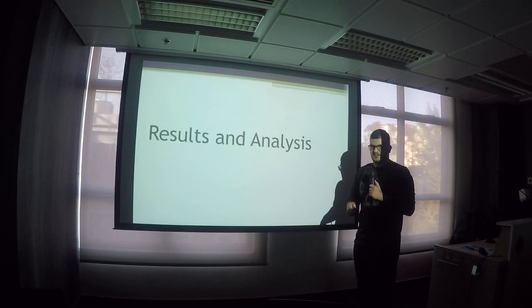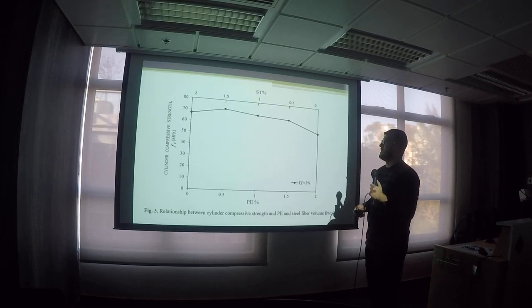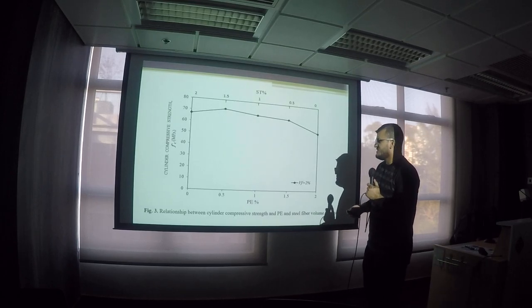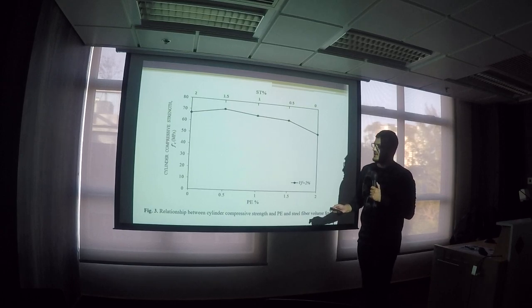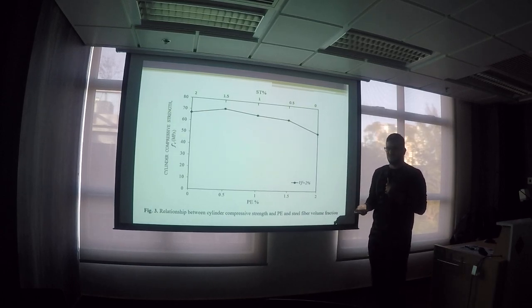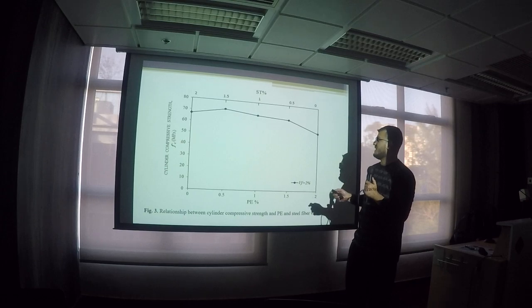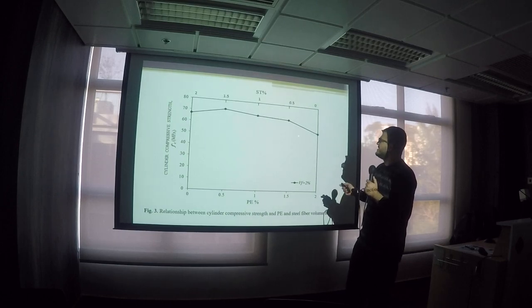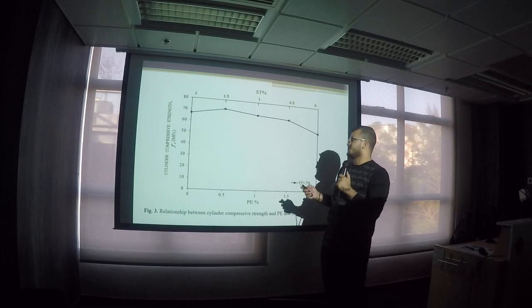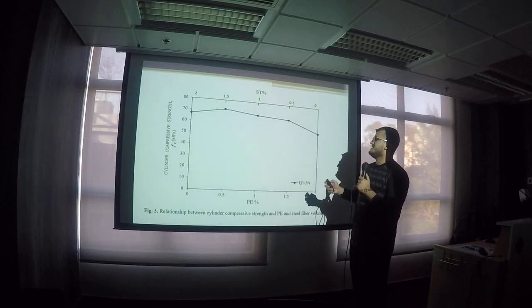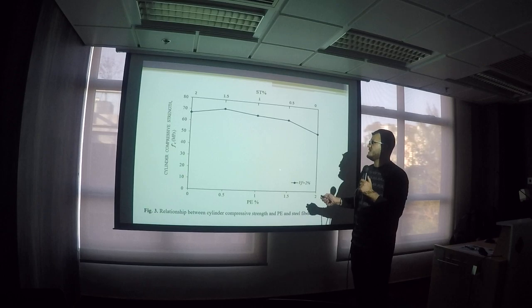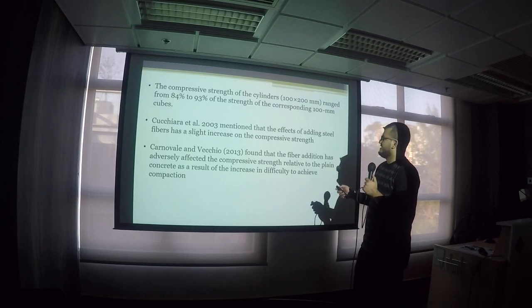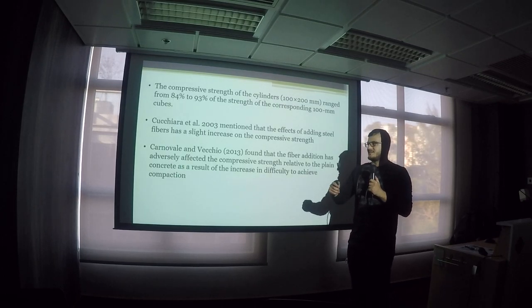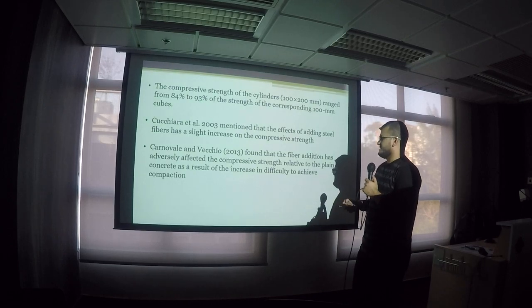Now let's jump into the results and the conclusion, which is the most important part. First, I would like to show the relationship between the compressive strength of the cylinders and the hybridization ratio between polyethylene and steel fiber. Generally, increasing steel fiber in the ECC composite slightly increased the compressive strength. This increase was a little bit shy, not that much, and actually this result was inconsistent with the previous research, as you can see here.